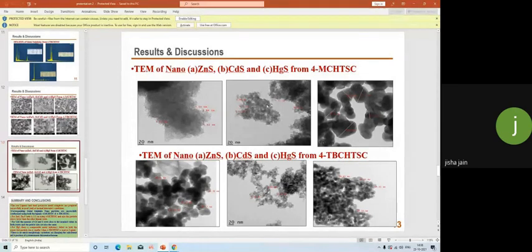In the case of cadmium sulfide, when 4-methyl cyclohexanone thiosemicarbazone is used, the particle size is from 5 nanometer to 8.83 nanometer. When 4-tertiary butyl cyclohexanone thiosemicarbazone is used as the ligand, the particle size is from 5.55 nanometer to 8.14 nanometer. The particle size is almost the same in both routes. In the case of mercury sulfide, with 4-methyl cyclohexanone thiosemicarbazone the particle size is 34.7 to 96.84 nanometer. With 4-tertiary butyl cyclohexanone thiosemicarbazone, the particle size is from 14.63 to 24.82 nanometer. It is clear that when 4-methyl cyclohexanone thiosemicarbazone is used, the particle size is greater.